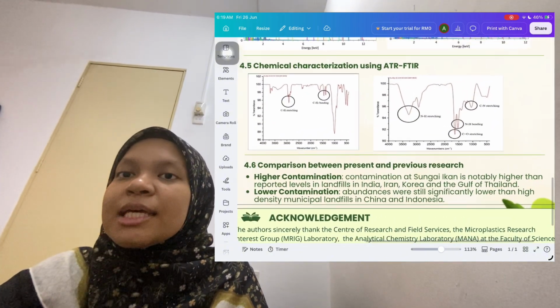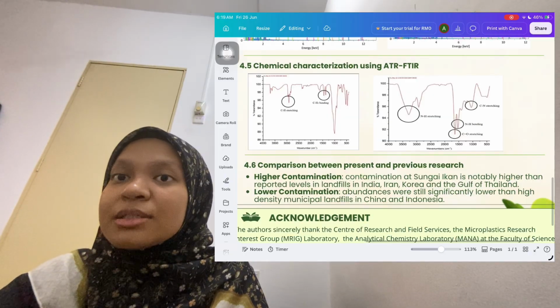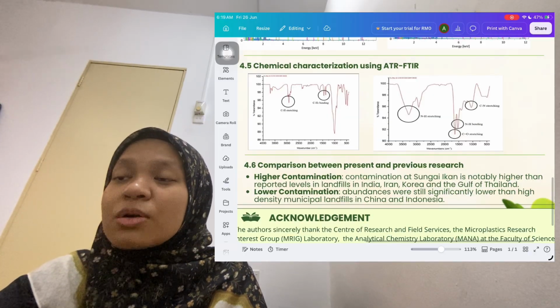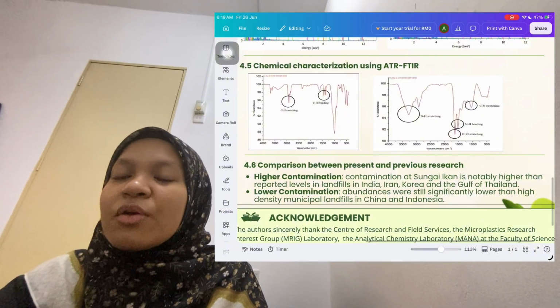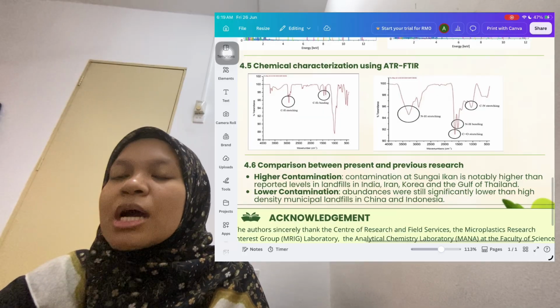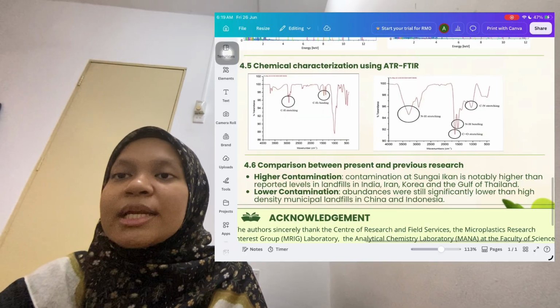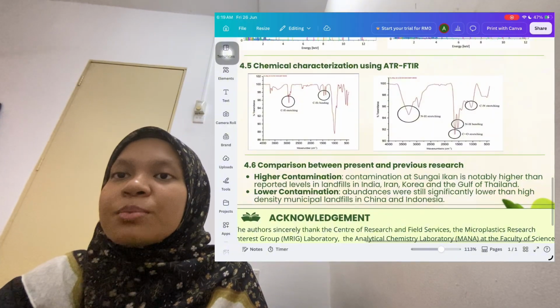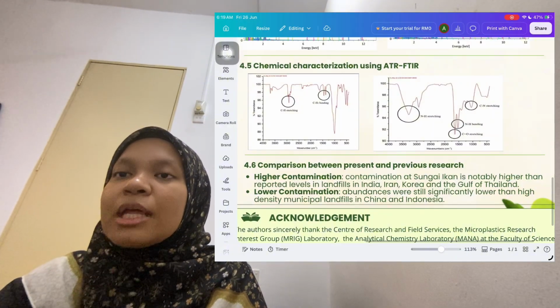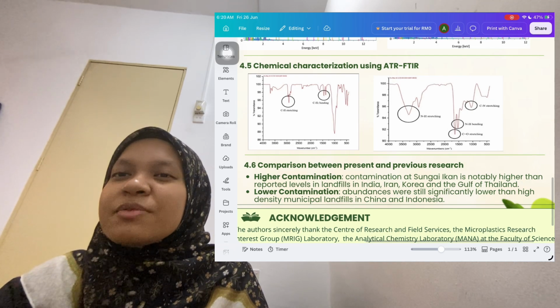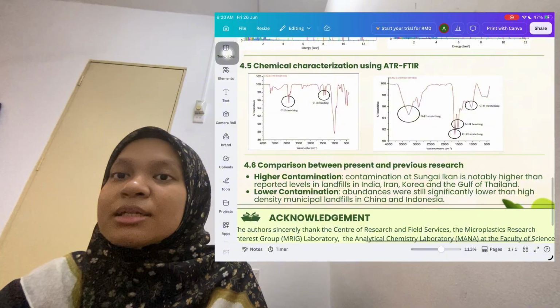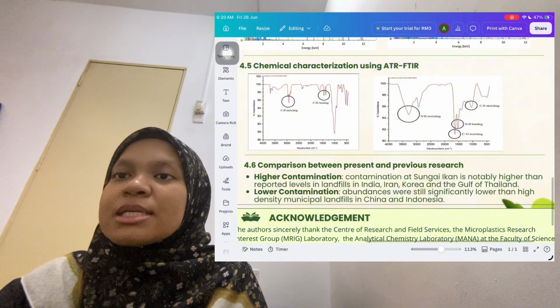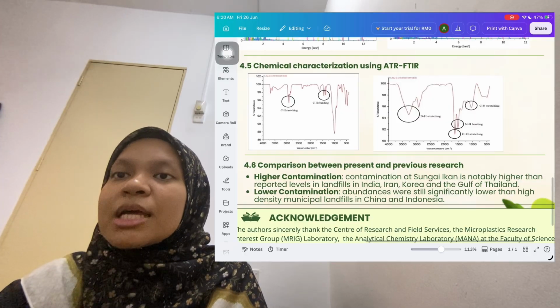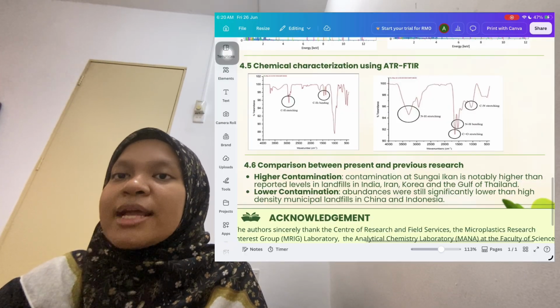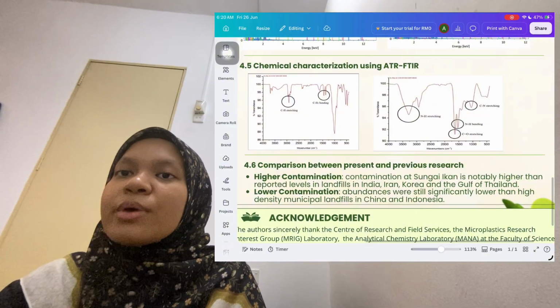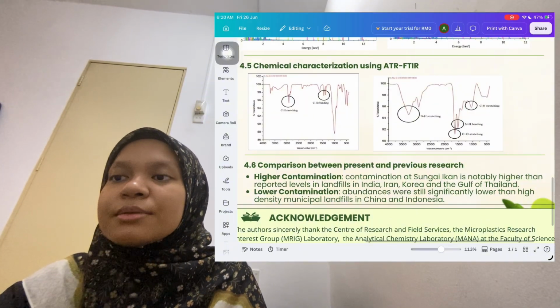When compared internationally, the contamination levels at Sungai Ikan landfill are notably higher than those reported in landfills across India, Iran, Korea, and the Gulf of Thailand. However, they remain lower than the ultra-high density municipal landfills found in China and Indonesia. The critical takeaway from these results is the clear environmental threat they pose. The combined effect of extreme physical weathering and toxic heavy metal absorption means these microplastics are transforming into toxic vectors. They present an immediate risk of leaching dangerous chemicals and heavy metals directly into adjacent soils and regional groundwater tables.